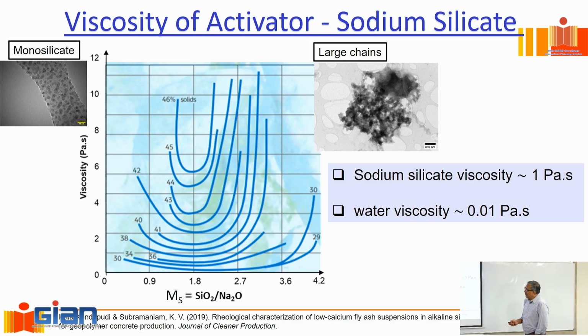Now, once I decide on a certain silica content, if I vary the MS, notice what happens to the viscosity. The viscosity first decreases and then it increases. The reason is that when the MS is very low, silica exists in monomeric forms. It is very close to monomeric or dimeric forms. It has not polymerized yet. As I start increasing the MS, which means the proportion of silica relative to sodium starts increasing, silica starts getting polymerized. So this is what I would get when it is highly polymerized. And the more it polymerizes, the more viscous it gets.